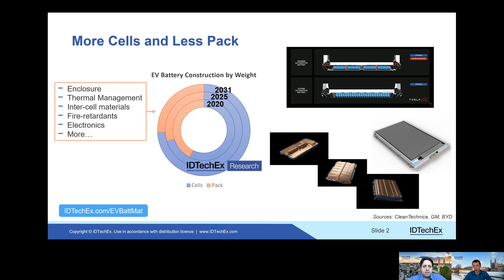We've seen announcements very recently from BYD, which you can see on the right here with their blade pack, where they have these long prismatic battery cells with very little material utilised around the actual cells themselves. We've seen GM with their modular system for the Ultium battery pack, again reducing materials around the cells. And then Tesla have even suggested their new cylindrical pack where the big new battery cells essentially don't have any coolant lines flowing between them like they used to, reducing a lot of extra materials. However, even given this reduction, a lot of these systems still require things like thermal interface materials, cushionings, and encapsulants. Even though we see a reduction per vehicle, the electric vehicle market is growing so rapidly that all of these materials still see an increase in demand.